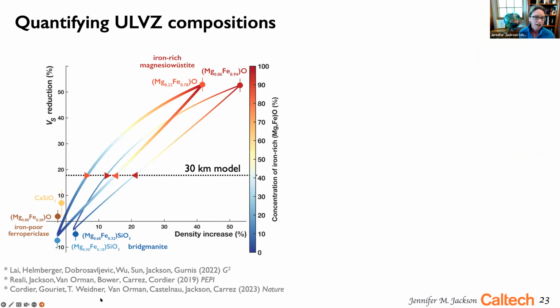And what we show here in the next slide is the S-wave reduction as a function of density for different mineralogical assemblages that bear this iron-rich magnesiowustite sample. The reason for the two different curves for each of these mixings, so we mix the silicate and the calcium silicate phase of the mantle, is due to the uncertainties in how those grains are interlocking, if they're in a uniform stress or a uniform strain environment. So a Reuss bound or a Voigt bound.